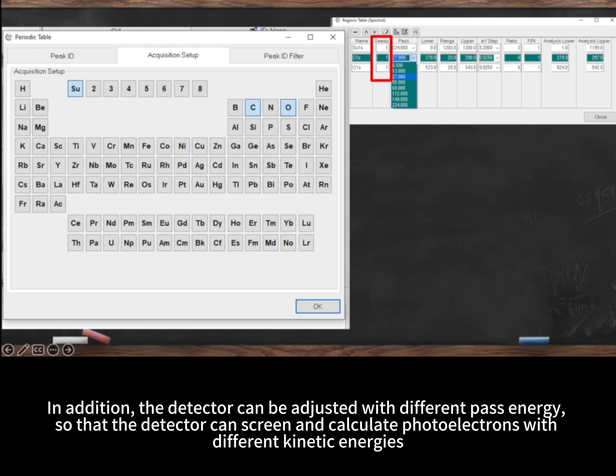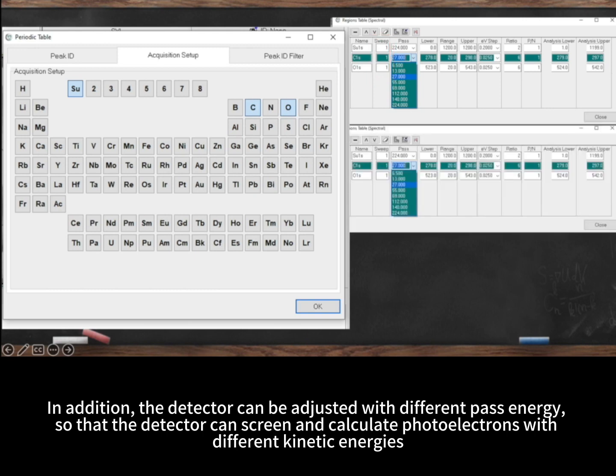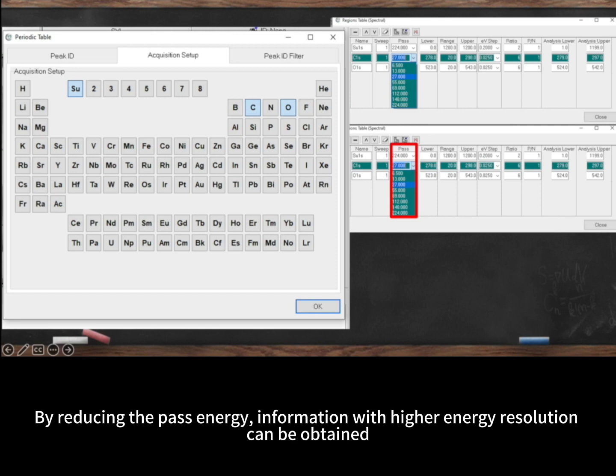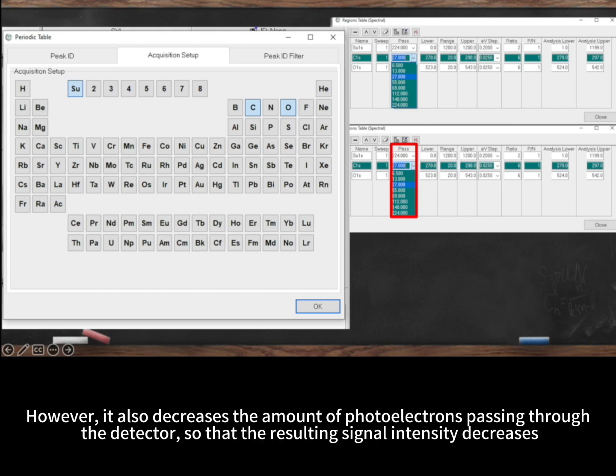In addition, the detector can be adjusted with different pass energy, so that the detector can screen and calculate photoelectrons with different kinetic energies. By reducing the pass energy, information with higher energy resolution can be obtained. However, it also decreases the amount of photoelectrons passing through the detector, so the resulting signal intensity decreases.